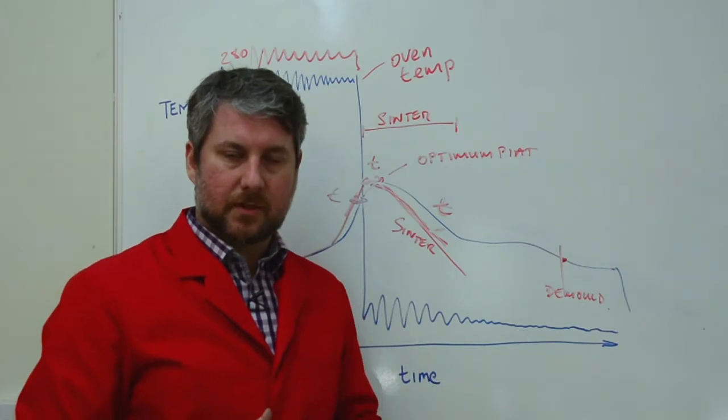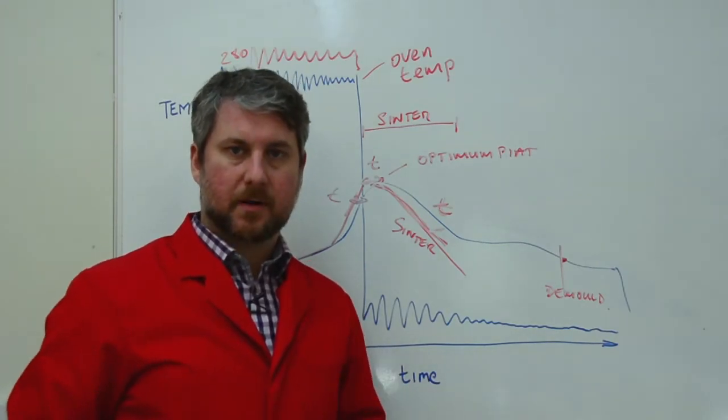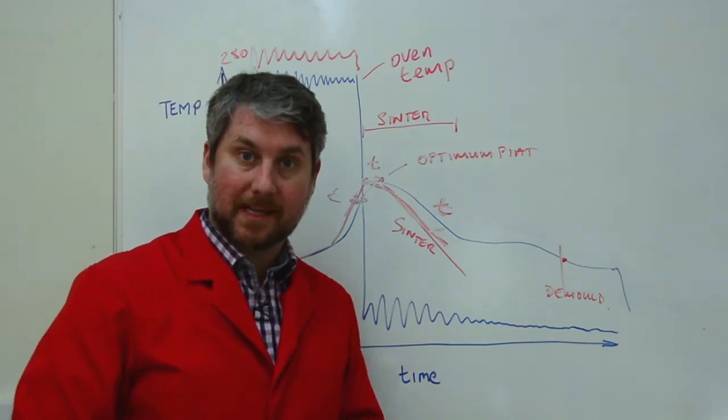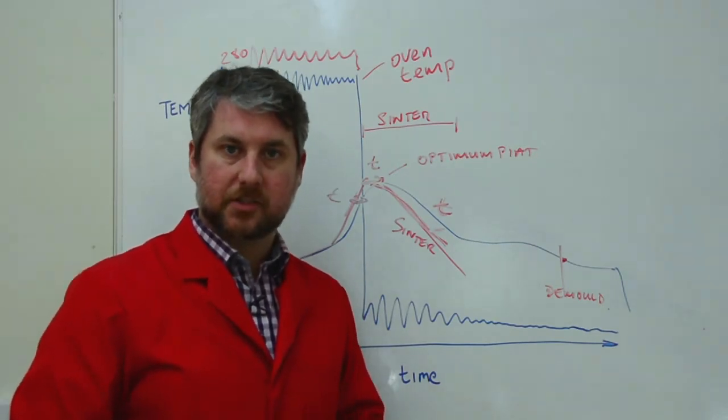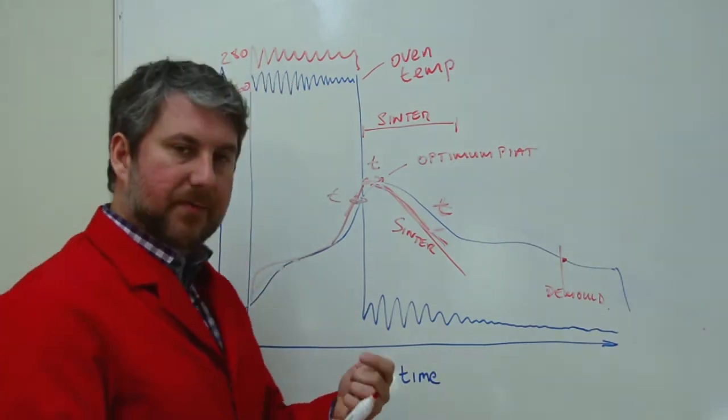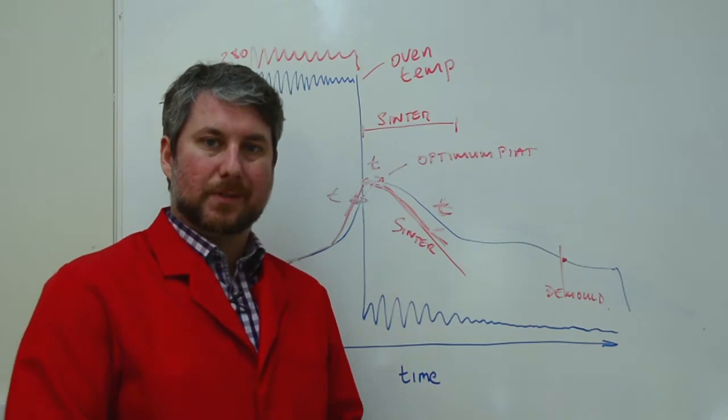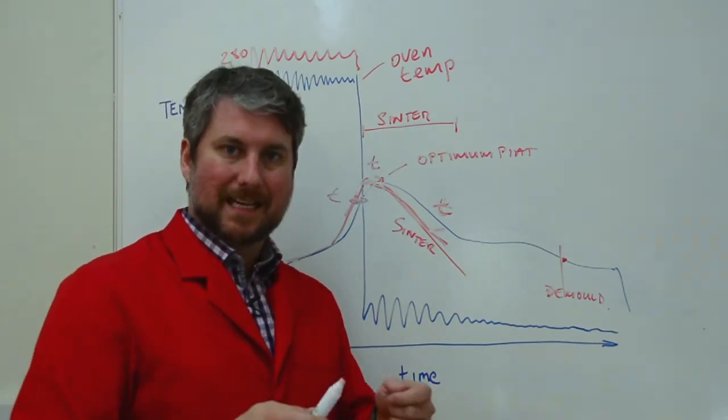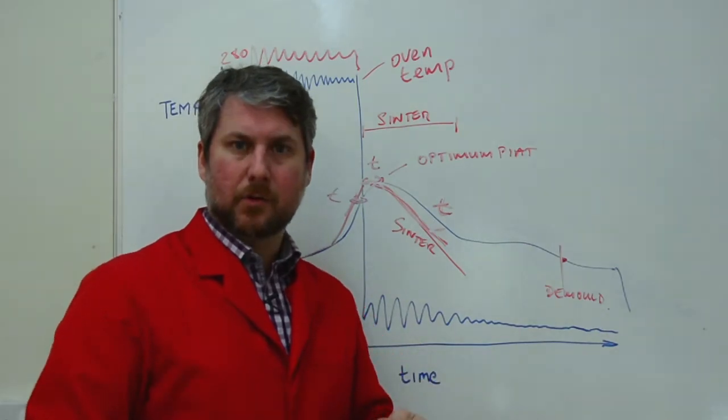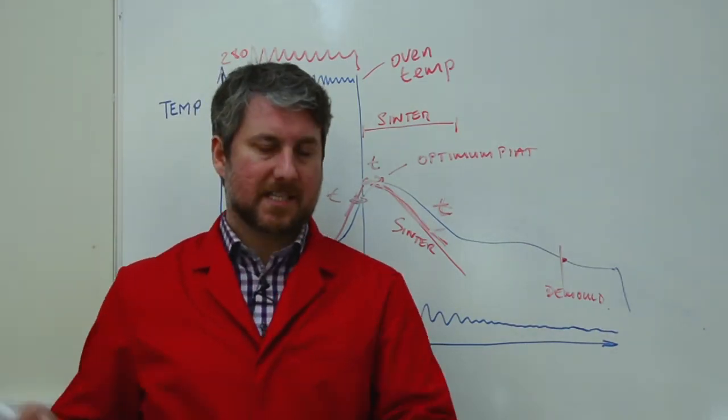So if you're wanting to keep track of quality of your parts, make parts that have similar shrinkage, similar warpage, then you need to get that part out of the mold straight away. The other thing to look at is what is the demold temperature? Not the time, the temperature.